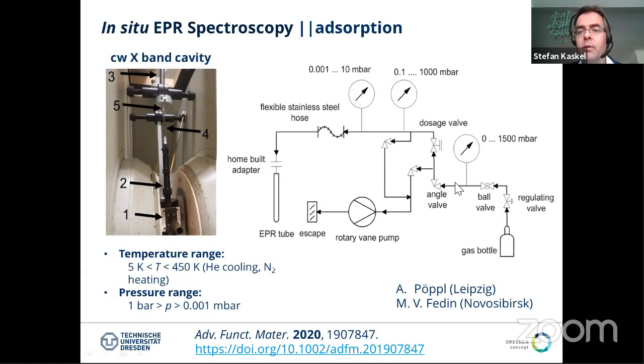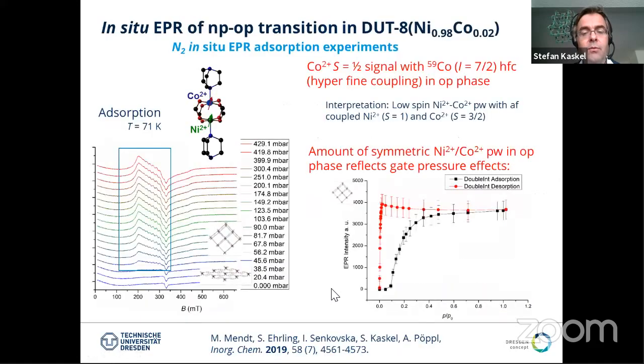And what we have to do is basically the same as before. We have to develop a dosing system that allows us to dose a certain pressure to the EPR tube. And we have to develop an adapter. And then we can put the tube into the cavity of the, here it's an X-band EPR spectrometer. And EPR spectroscopy is very valuable because it covers a wide range of temperatures. And with this dosing system, we can cover a wide range of pressures. And I would also like to point out that the group of Fedin in Novosibirsk is also one of the pioneers in this field. So both these authors are certainly highly recognized experts in this field.